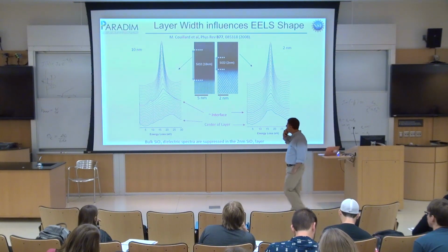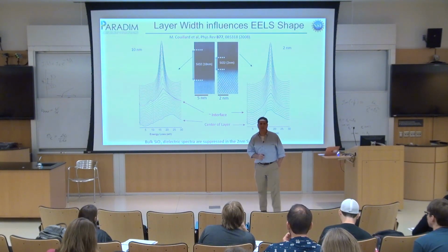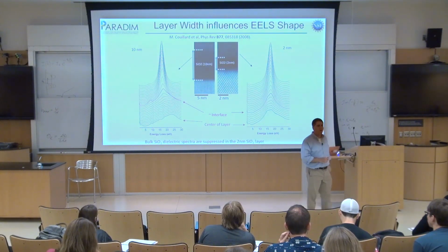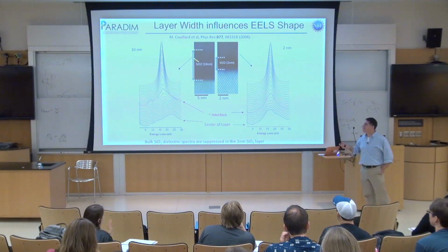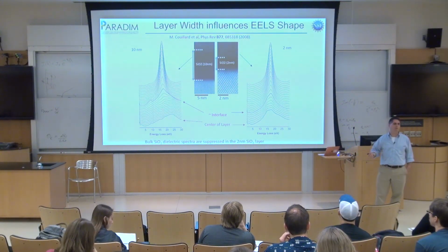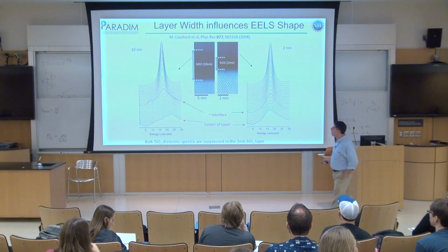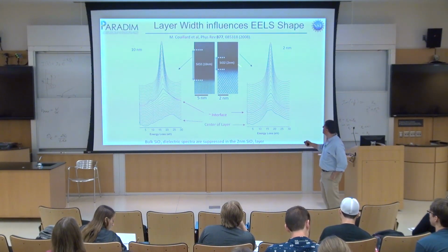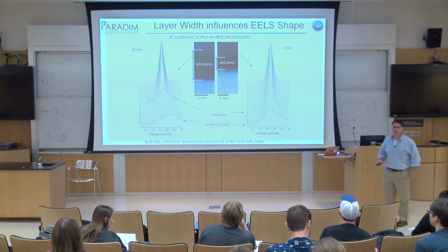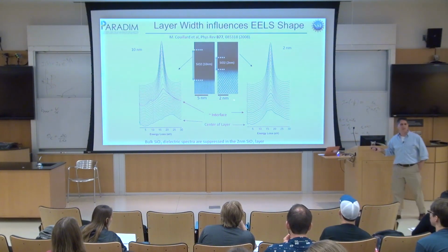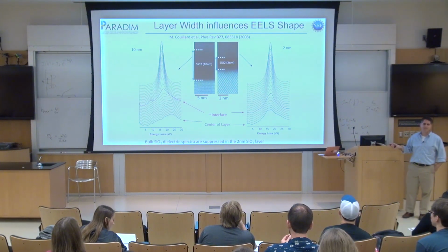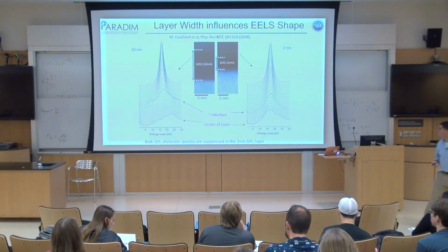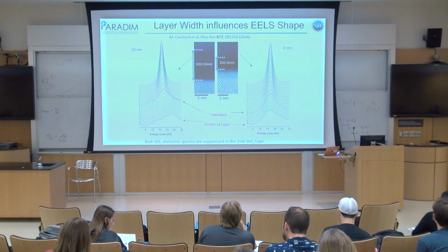We're going to hear on the weekend a lot of talk about valence EELS with phonons. Phonons use not 10 eV energy losses. They use 0.1 eV energy losses. v over omega is going to be hundreds of nanometers. You take exactly the same problem, you rescale it, and you say, well, I shouldn't be seeing any phonons in thin films. Or at least you'll see things, but they won't be from the layer you thought they were.